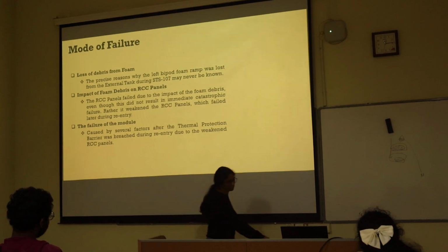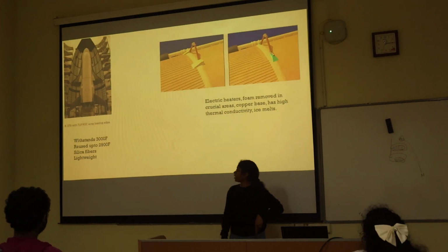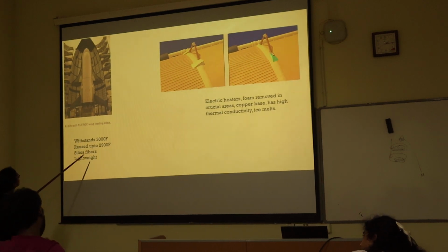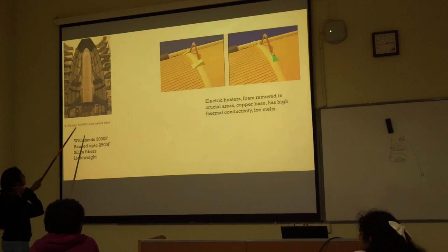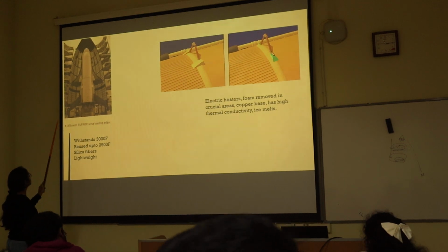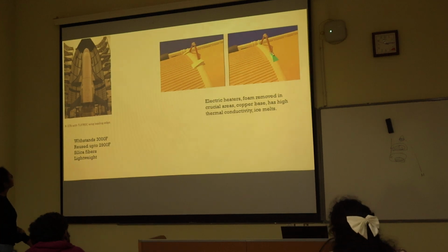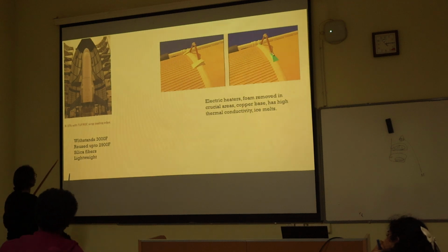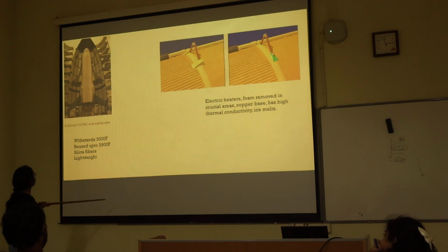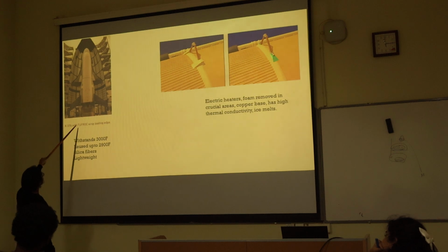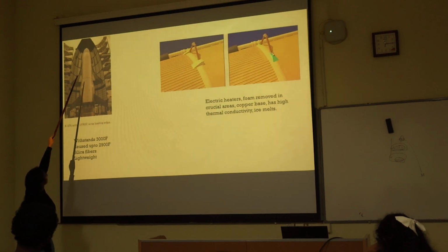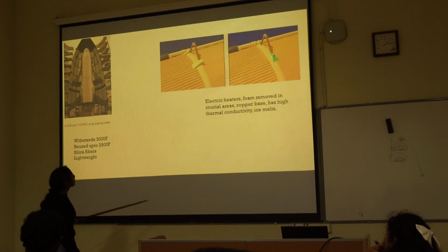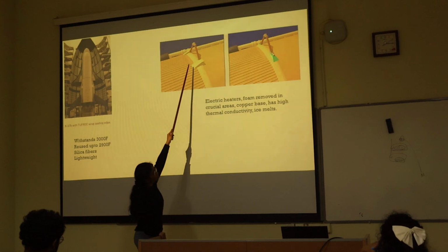So we look at that. Yeah, again, firstly, there's something called TUFROC. This is a new material after the Columbia disaster, which can withstand up to 3000 degrees Fahrenheit, and you can also reuse it unless it experiences around 2900 or higher temperatures. It's made of silica fibers and it's lightweight, and it's used at the leading edge again. TUFROC is used, as I mentioned, at the nose and the front ends of the left and right wings. And so the problem was because of the foam.